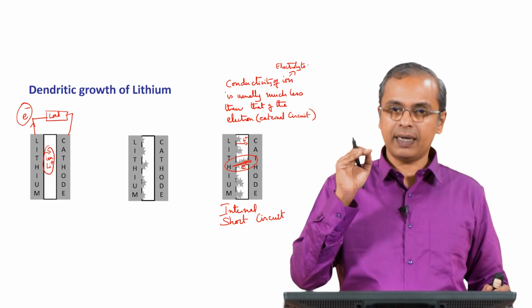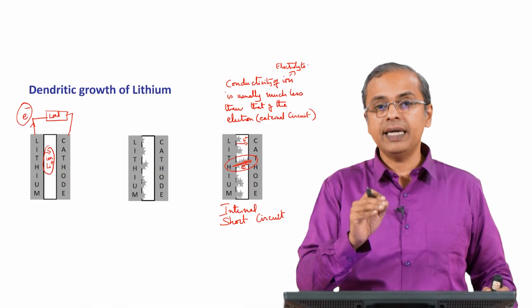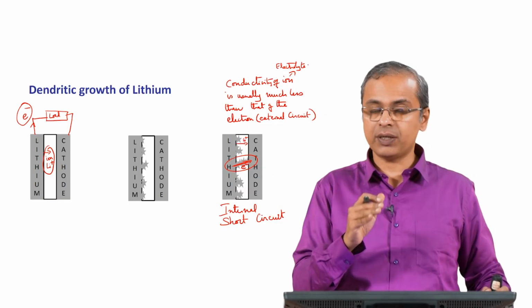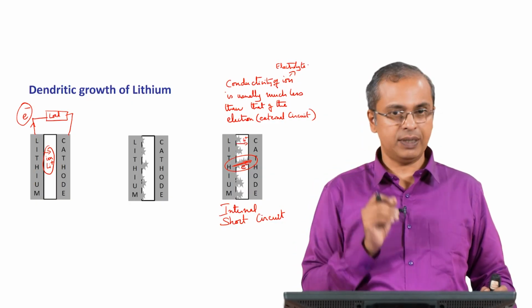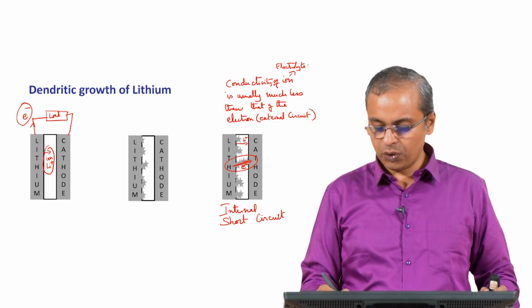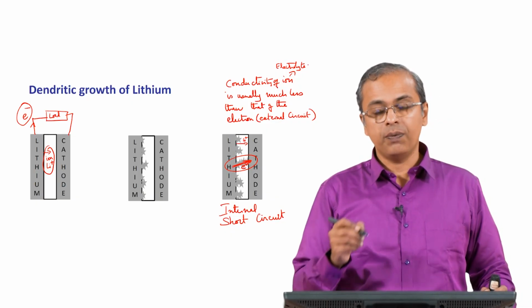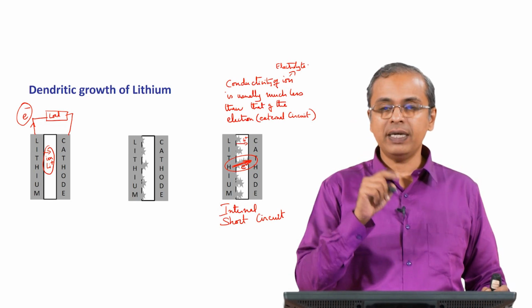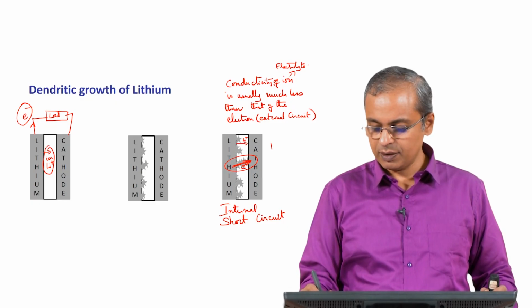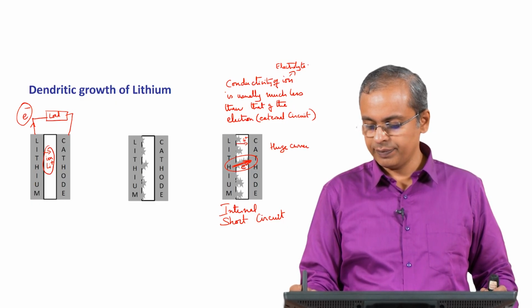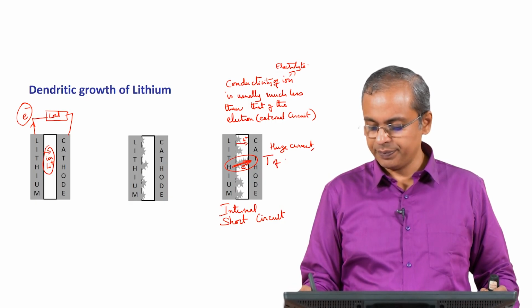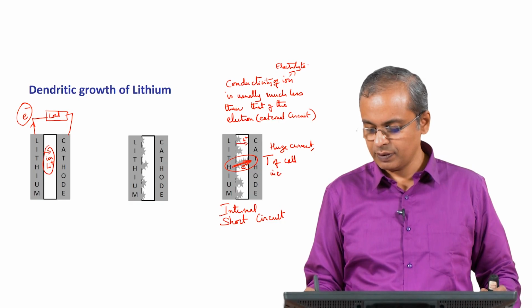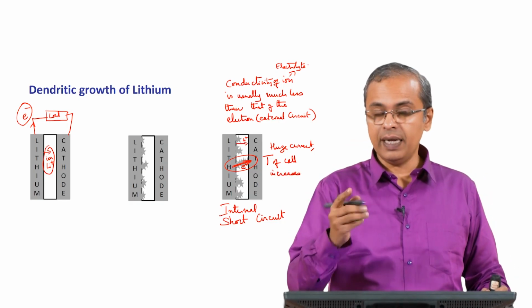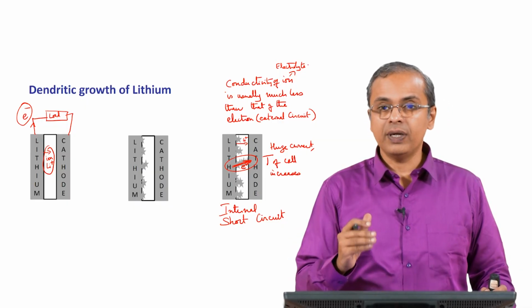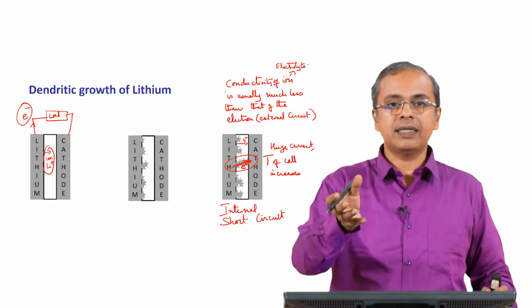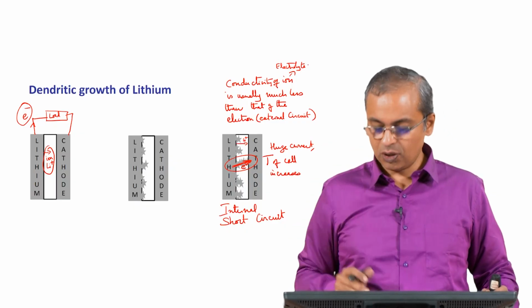Interestingly, the conductivity of electrolytes or ionic conductivity of most materials increases with temperature. Okay. Unlike electronic conductivity, which actually decreases with temperature, ionic conductivity increases with temperature. So, now when you have an internal short circuit, you have a lot of current going through this internal short circuit. When you have a lot of current going through a pathway, that pathway heats up. So, because of this huge current, temperature of the cell goes up, increases. If temperature of the cell increases, it increases the conductivity of the ion. If you increase the conductivity of the ion, the current in the cell further increases. Okay. So, this is called a thermal runaway, Okay.